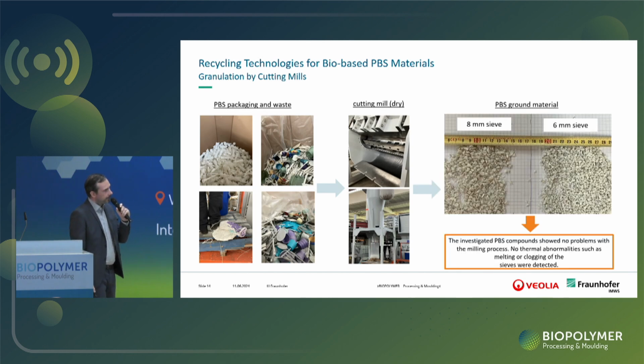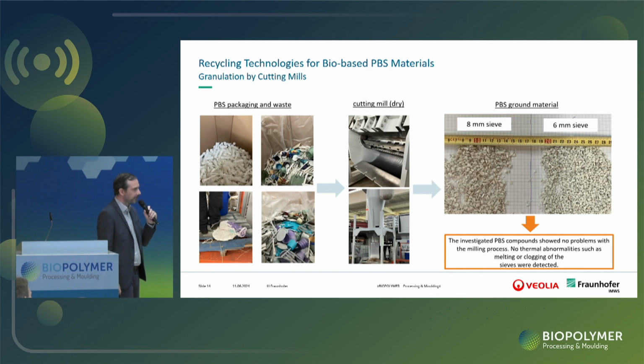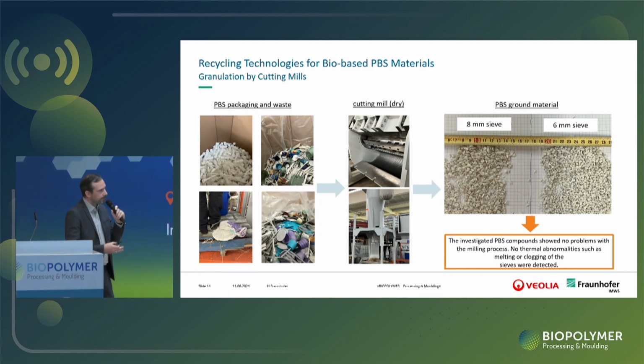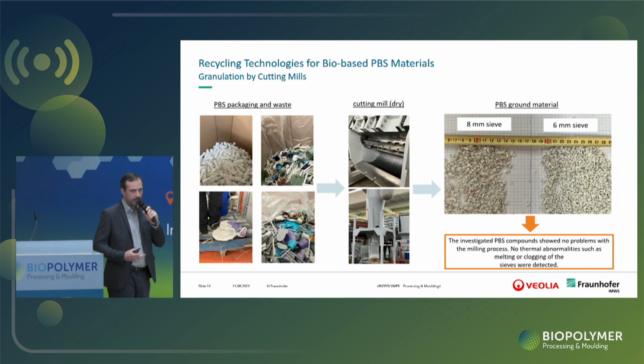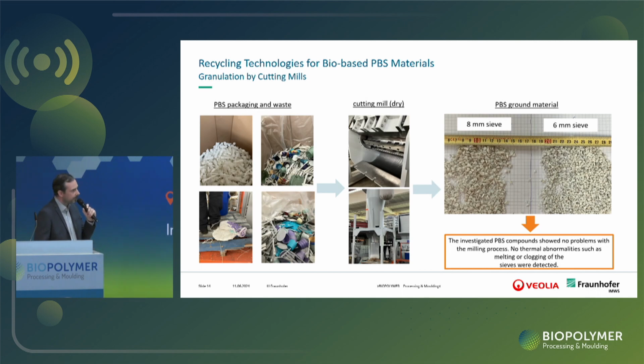recompounding and reprocessing. And here we worked also with an industrial mill. The throughput was 800 kilos per hour. So these are the throughputs of industrial mills in this scale. And you can see also with different sieves, 8 millimeter and 6 millimeter sieve, we got this ground material with different sizes of the pellets. And there was no problem at all, even at this high throughput to grind and mill the PBS products. Even with a dry mill, so there was no water needed to cool down the mill and so on, which is also important information because PBS as a polyester is not very good to get in contact with water. You must do a lot of drying afterwards and so on. So this is not necessary here. So also the milling, the grinding of the material in the next step was no problem. And here we work together with Veolia.